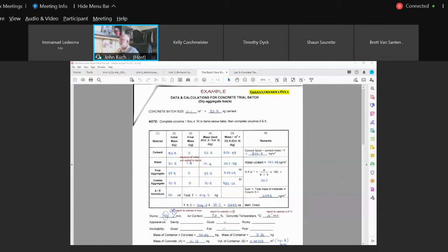But if you come in with mix design A and one load is 70 and one is 110 and one is 50 and the other one is 140, another one is 90 and another one is 75, what's happening? Why is it all over the map? That's non-consistent. So workability is not dictated or determined by slump, and not water cement ratio, because there's a lot of factors that affects the slump other than water. Yes, water may be one of the biggest culprits of changing slump, but the sand grading can change, the ratio between sand and coarse can change. Admixtures can change. A job arrives at a job site and all of a sudden you see a slump of 140. Should you panic without knowing anything about it? Anybody?